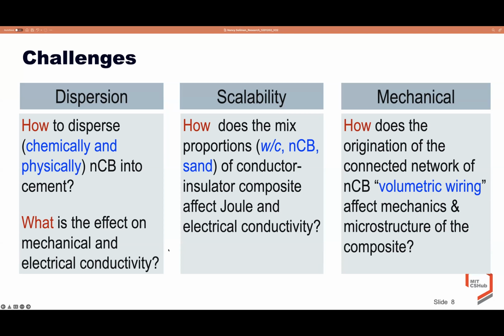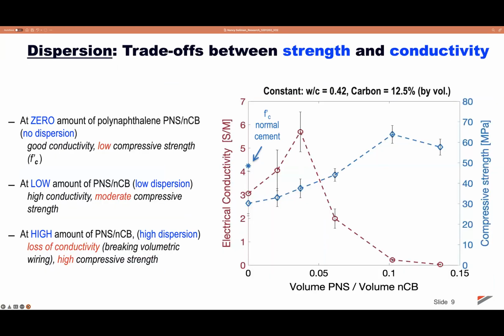The third question here, to get the full advantage of multifunctional material: how does the orientation of the connected network, the volumetric wiring, affect the mechanical properties and the microstructure of the composites? Here, I will present some of the results about the effect of the chemical dispersion of nanocarbon black particles. We use several surfactants such as cellulose, polycarboxylate superplasticizer, polynaphthalene, and a synergy between both the cellulose and the polycarboxylate superplasticizer.